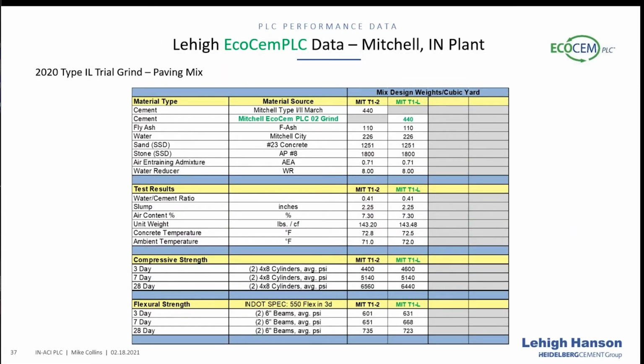I think one of the best uses for PLC is in a paving mix. I just think that extra fine content from the limestone makes it work fantastic through a slip form paver. So we wanted to see how this would perform in an everyday paving mix. We did 440 pounds of cement with 110 pounds of F-ash, used air entrainer and a water reducer. Here's the plastic data from that testing. We had a 0.41 water-cement ratio in both mixes and got 2 1/4 inches of slump.